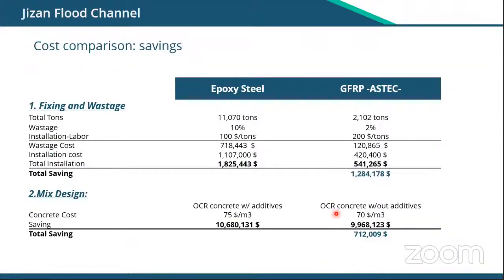Typically, the contractor would save on steel fixing, while fixing GFRP costs on average double that of steel. Since you put 5.5 times less reinforcement, there was a big saving there, also on wastage. There's also saving on the concrete mix, as I mentioned earlier. And one of the big savings that was not implemented here is that the quantity of concrete could have been reduced further from the concrete cover, but again, not on this project.